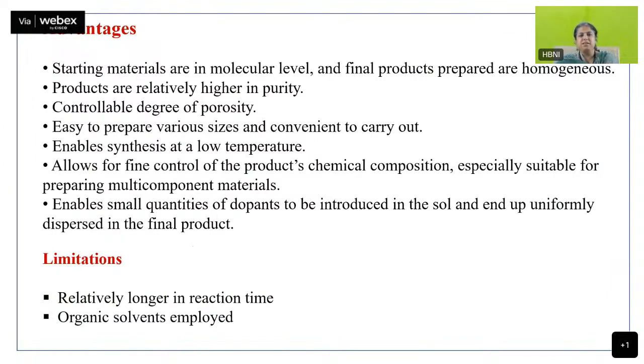Advantages: because you're mixing them all in a solution, right? So the products are homogeneous. They're high in purity. You can control the powder properties, porosity, particle size, okay? Low temperature synthesis, then allows for fine control of the chemical composition. So if you want to make a 3, 4, 5, 6 component containing oxide, this is one of the best methods. Enables a smaller quantity of dopants also to be introduced, and then it can be dispersed.